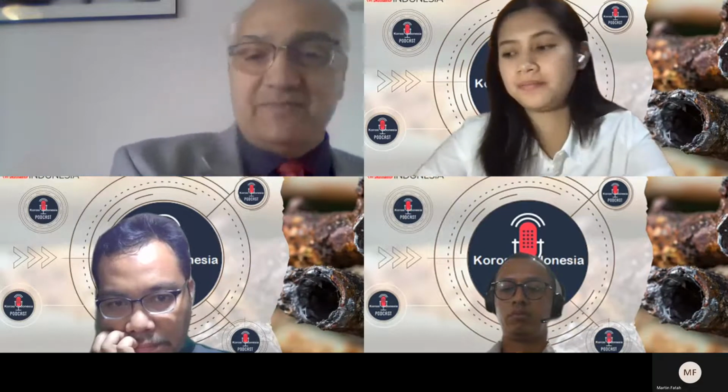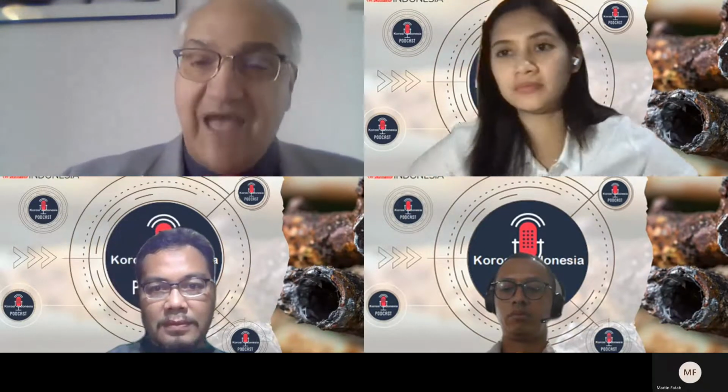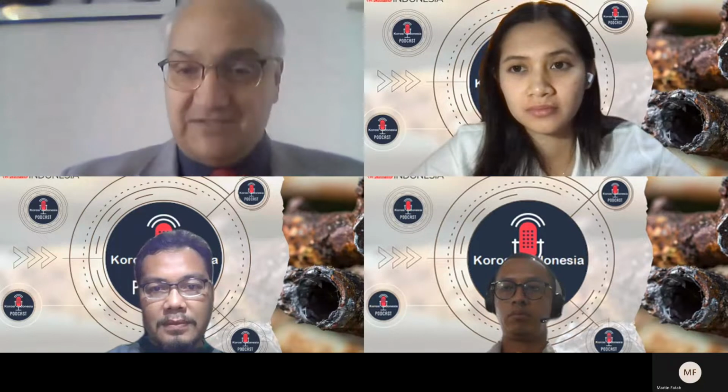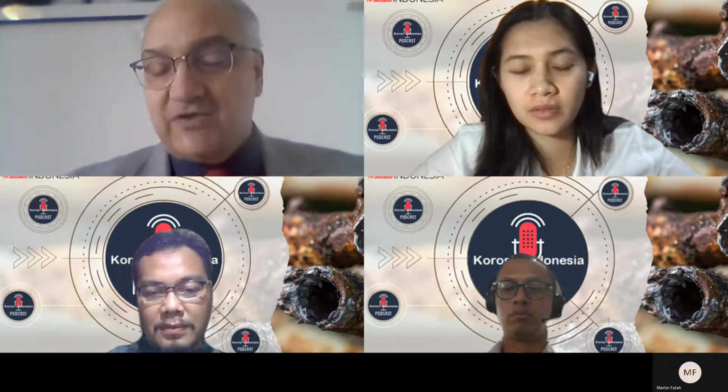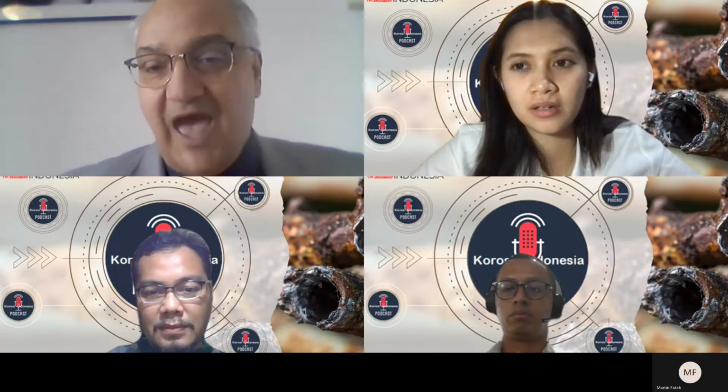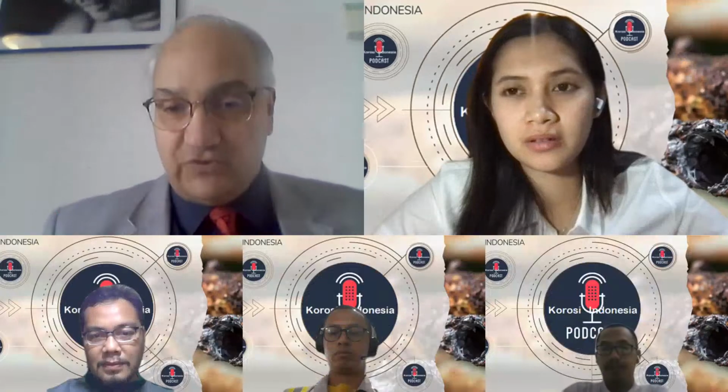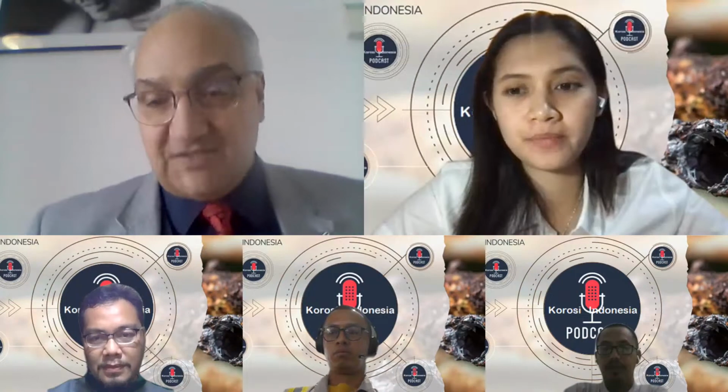So I took it to the laboratory, dried it, and then applied a magnet. Okay? And it stuck to the magnet. It was magnetite, Fe3O4. And the other layer was hematite.